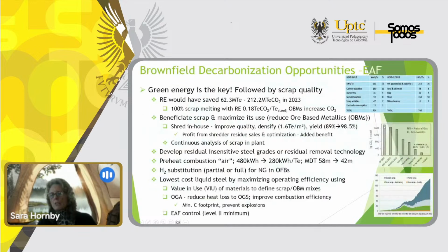the improvement from blast furnace BOF down to hybrid, which is the hydrogen DRI EAF melting. Any increase in what we call ore-based metallics, the DRI, HBI, or pig iron, is going to increase your amount of CO2 generation, as you can see, moving upwards. This is DRI EAF. This is DRI EAF with renewable energy. Scrap, and then scrap EAF with renewable energy. You need to beneficiate the scrap and maximize its use, obviously, because of that.